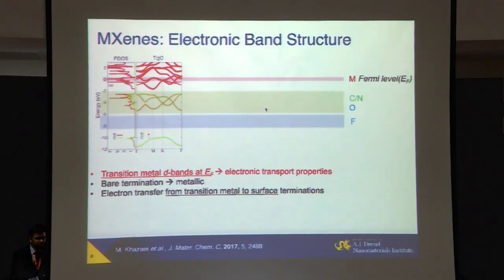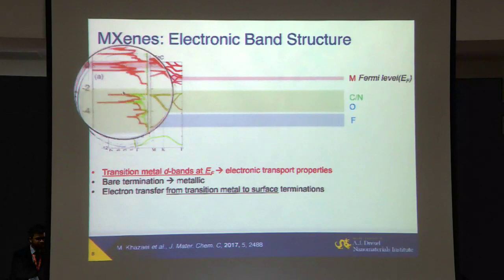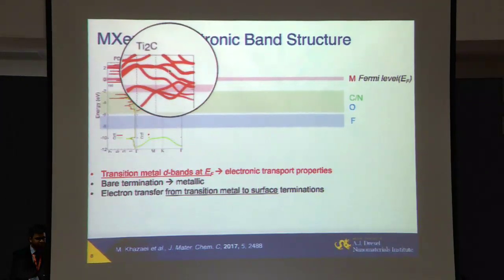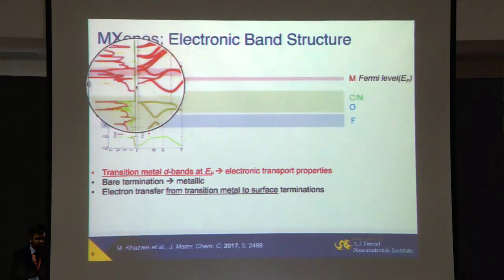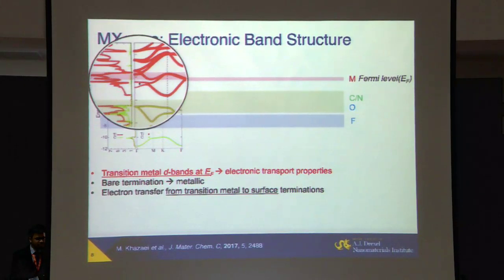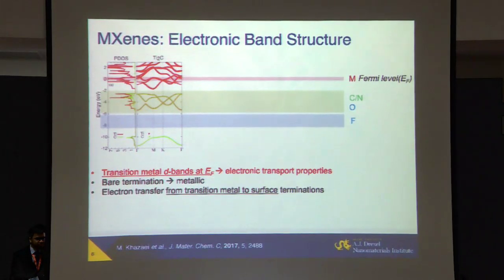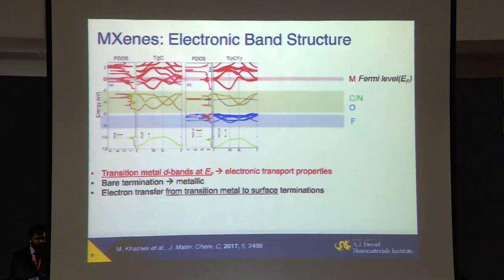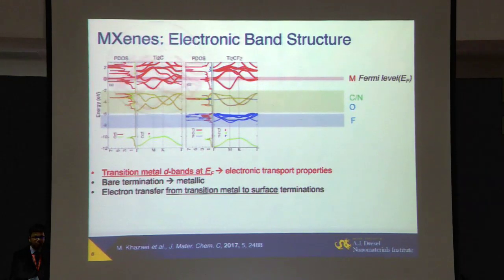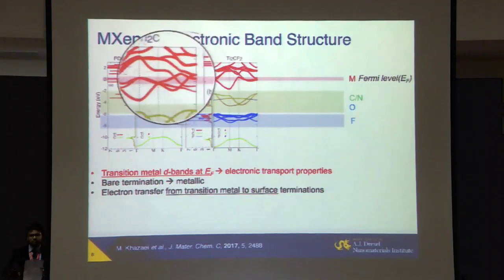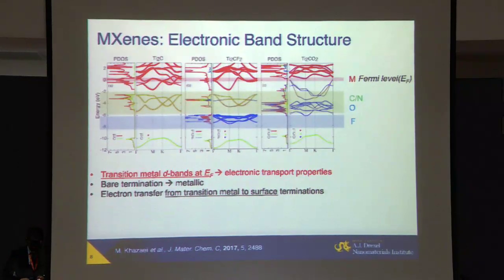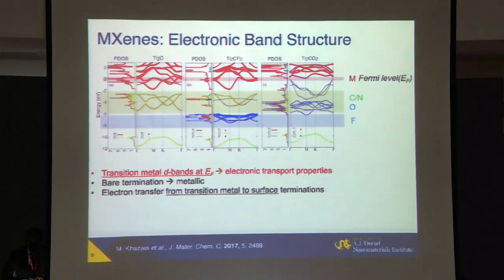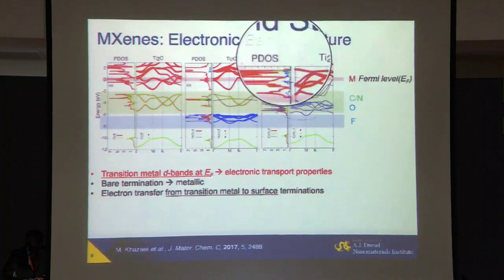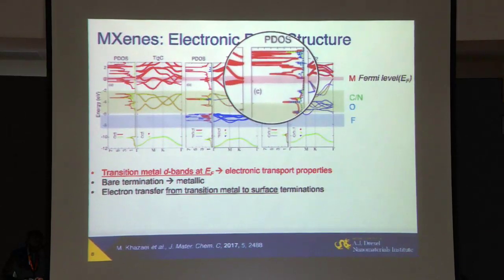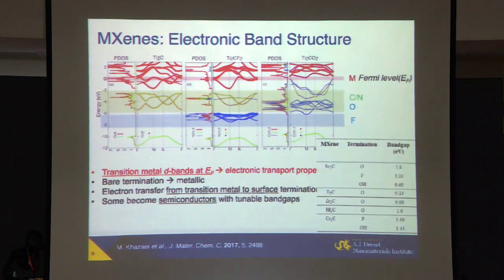I'm going to give you a few examples today. But one thing I wanted to mention, which is really important here. If you look at the band structure of, say, this is an example for titanium carbide Ti2C, one of the first discovered, actually discovered at the same time, but published a little bit after Ti3C2. You see there is a high density of states at the Fermi level when the material is terminated with no surface groups here. If we change the termination, we put fluorine termination on the surface, the density of states decreases. But if you put oxygen on the surface and pull two electrons from every titanium atom, like in the Ti2CO2 structure, you can even open the band gap in this material.